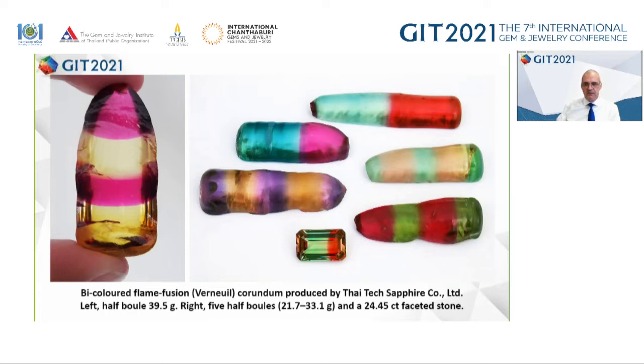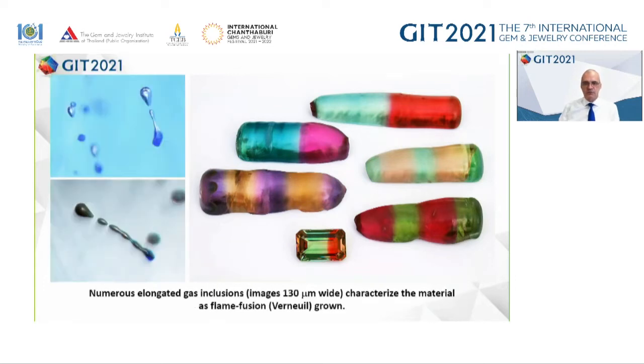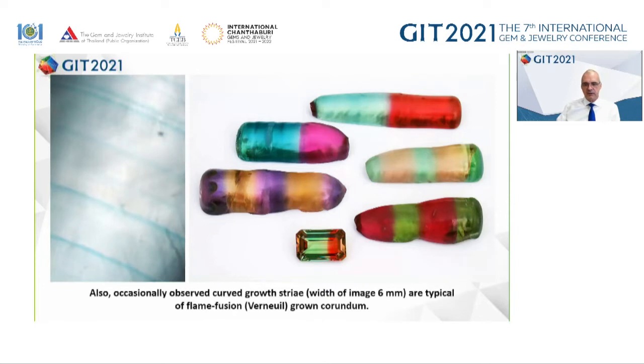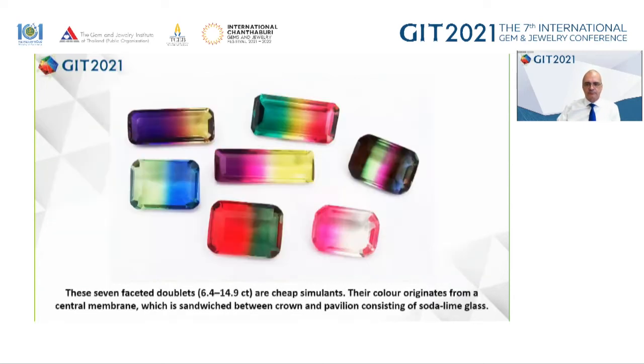It's fairly easy to distinguish it from natural stones, not only from the sometimes odd coloration, but we have these typical elongated gas inclusions that are very typical of Verneuil grown corundum. And in some cases, we also can see such curved growth zones or stripes that, of course, tell us very easily under microscopic observation that we have a synthetic stone here.